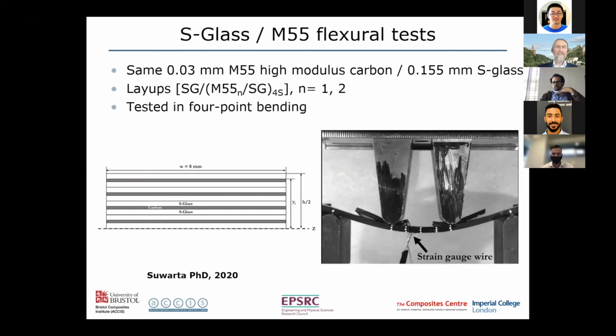So moving on then to look at the flexural behavior. Here we're taking the same 0.03 millimeter M55 high modulus carbon and the standard thickness S-glass plies, but now we're laying them up right the way through the thickness and testing them in 4-point bending. Again, we've changed the number of these M55 plies to be either a single ply or a double ply.